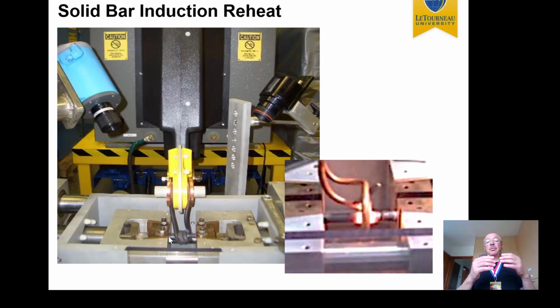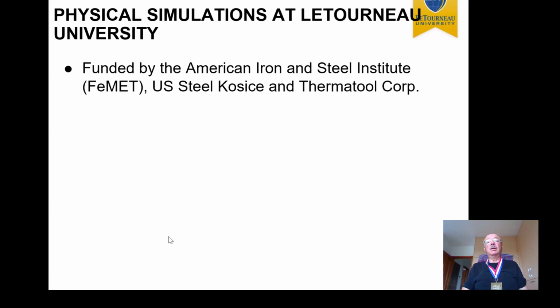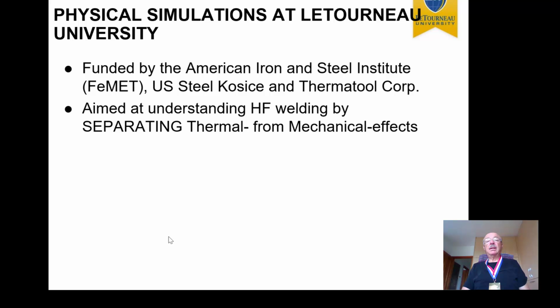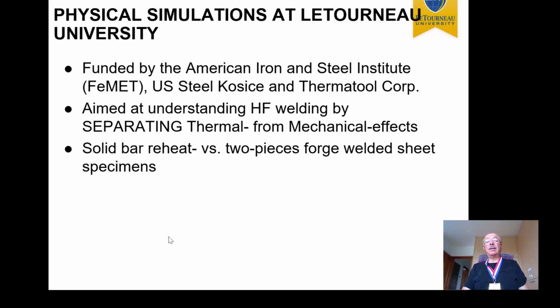We used solid bars. Then we used pairs of bars, and we basically welded them together to reproduce high-frequency welds in a highly controlled condition in order to separate the thermal from the mechanical effects. That was the purpose of this work. This was funded by the American Iron and Steel Institute. Later on, U.S. Steel and Thermatool participated in funding. Again, we were aiming at separating thermal from mechanical effects.